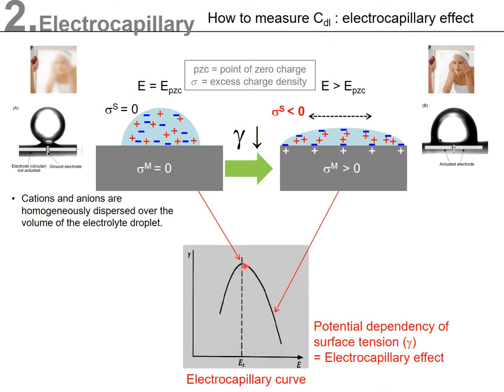However, when we go to a potential far from the point of zero charge, sometimes in the positive direction, sometimes in the negative direction, the surface tension of your droplet or electrolyte would decrease in both directions. This curve of surface tension versus potential is called the electrocapillary curve. And this potential dependency of surface tension is called the electrocapillary effect.